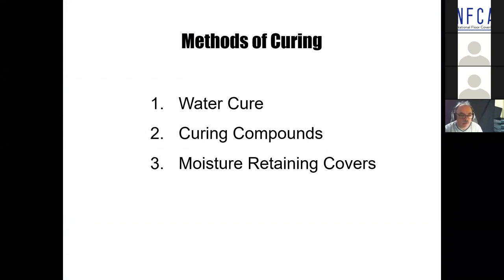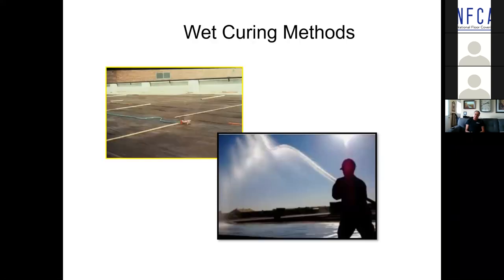Well, if concrete could vote, it would jump up and down to be water cured. But water curing, while a very effective method, isn't easy to do, isn't always practical, particularly on elevated slabs. And you absolutely have to avoid an alternating wetting and drying and wetting and drying. And I'm still of the opinion, because I have seen it happen, that when hydration takes over in the summertime, the temperature of that slab after it's finished can reach 120, 130 degrees Fahrenheit. You hit that with 55-degree water out of the ground. I've seen it craze and crack the surface of the slab. So water curing isn't always the most practical way for curing slabs that are going to receive a floor covering or a coating system.